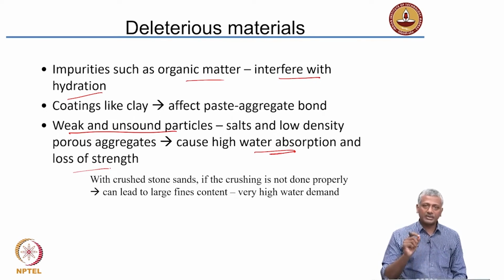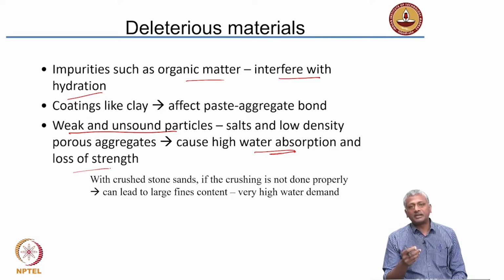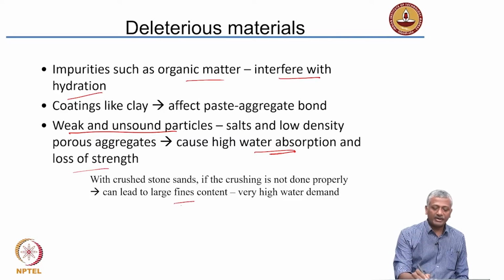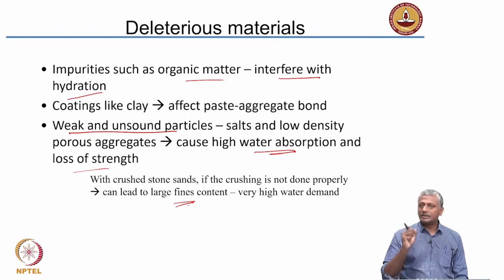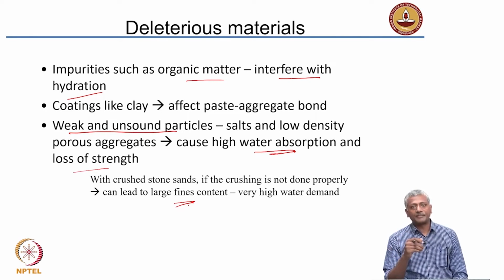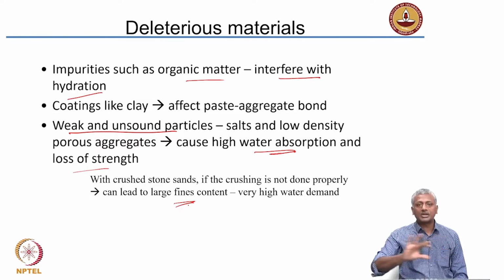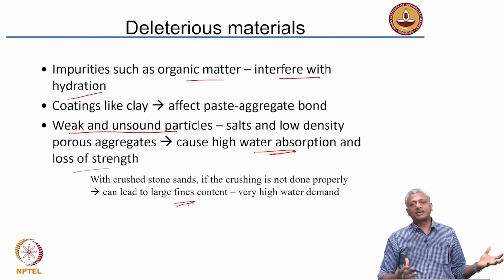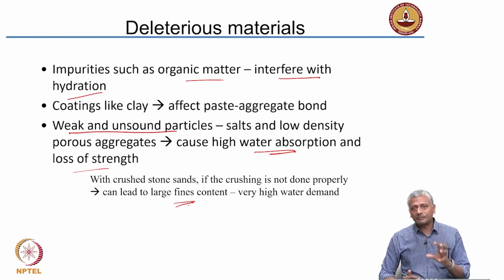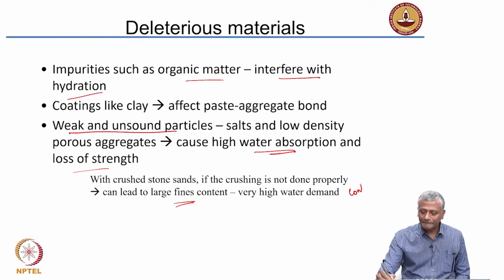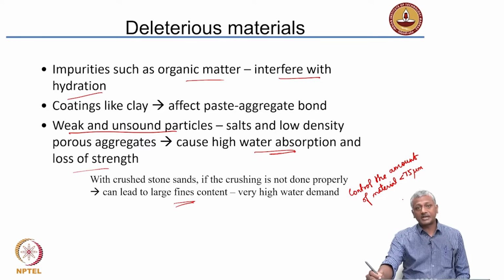What happens is, when you crush the stone as sand, depending upon the type of mineral that goes into making the stone, you get a very large quantity of fines. When you crush the stone through improper techniques, you can actually get very large quantities of fines. Even with a good crushing process, you will still get a lot of fines, and you need to take care that the fines are washed out or removed through some classification scheme, so that you can get a good quality aggregate which has the right size. So, you need to control the amount of material which is lower than 75 micron, because that may be silt or clay.